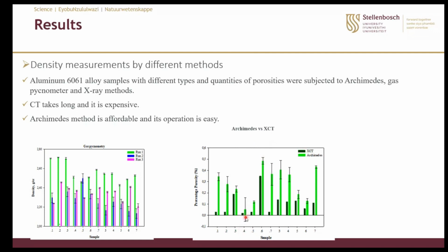So we took the lowest porosity sample and used it as the reference density. From the results, we compared the computed tomography and the Archimedes, and we could see that both had porosity less than 0.5%. However, the correlation is very poor between these two methods. This could be because, even though Archimedes can miss porosities that are filled with powder, computed tomography can also have issues like lack of resolution and errors in the segmentation, such as missing very small porosities, hence the lower porosity values when compared to Archimedes.